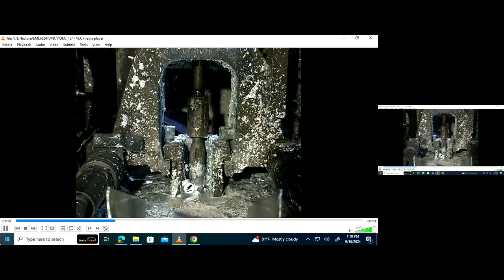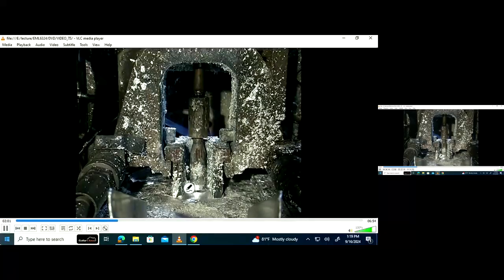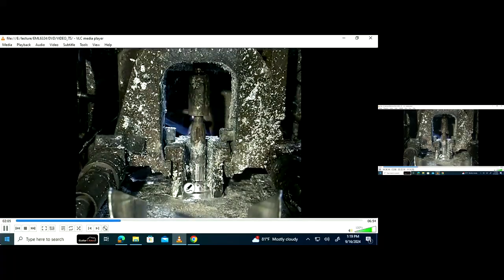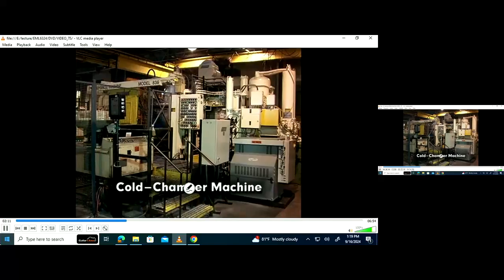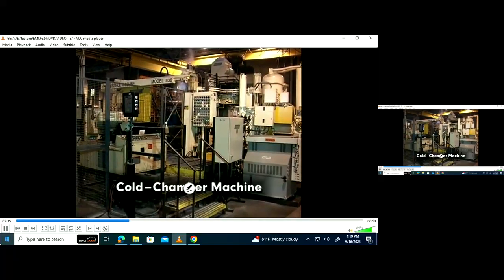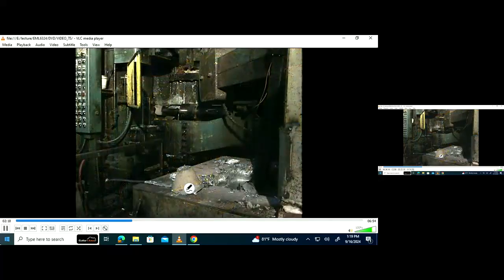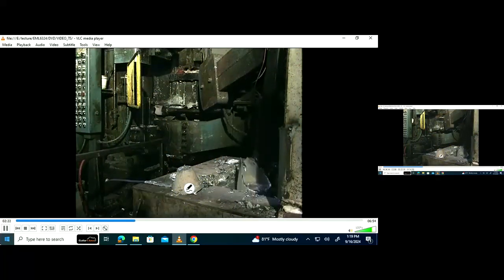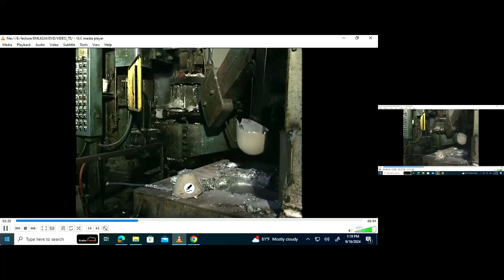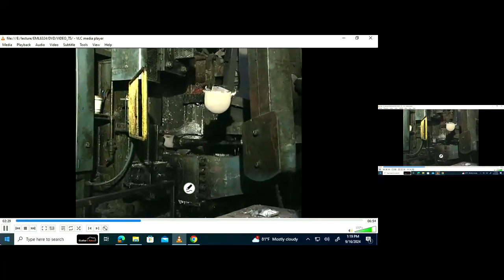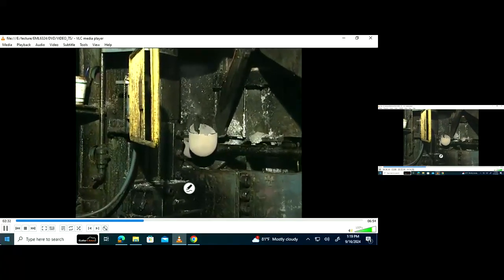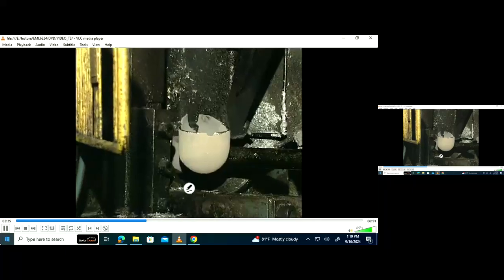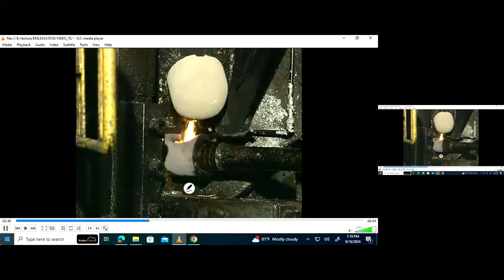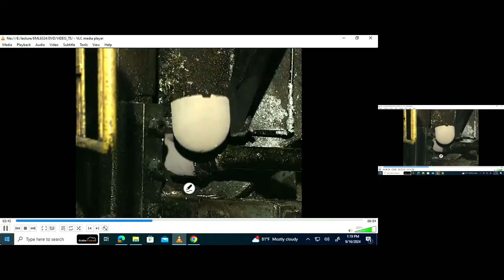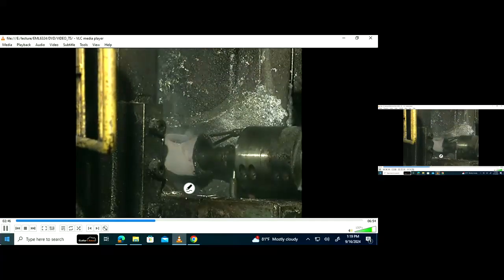Injection pressures may range from 1,500 to more than 4,500 pounds per square inch, or 10 to 31 megapascals. The cold chamber machine is used primarily to die cast the aluminum, magnesium, and copper alloys. In the cold chamber machine, the charge is supplied by ladle or feed system from an external furnace source to a holding pot at the shot end of the machine. The feed system components are not submerged in the molten metal. The charge is poured ahead of the plunger tip through a pour hole in the shot sleeve. As the plunger advances, it closes the pour hole and drives the molten metal into the die.